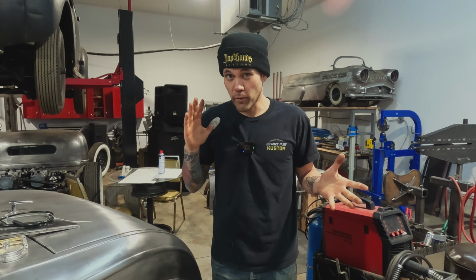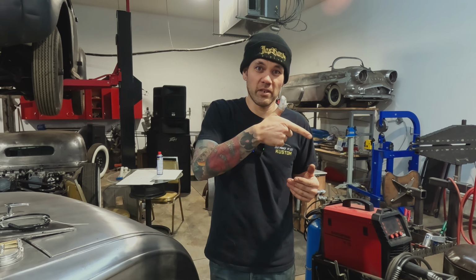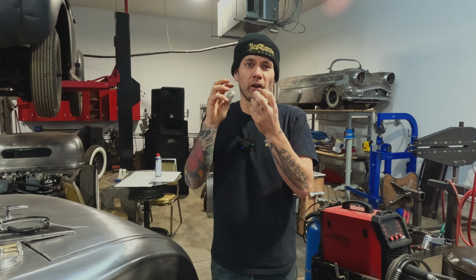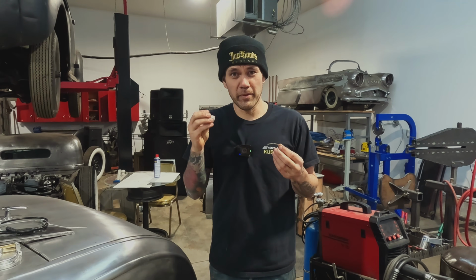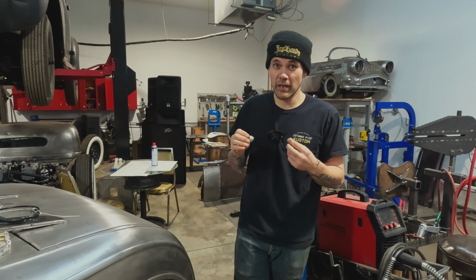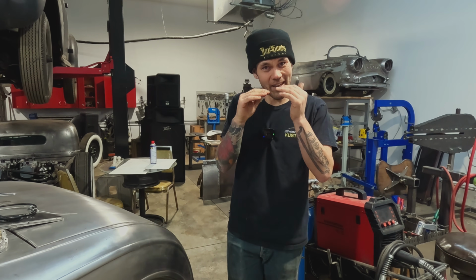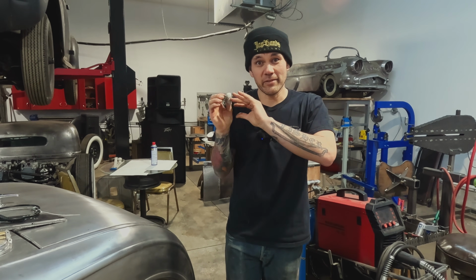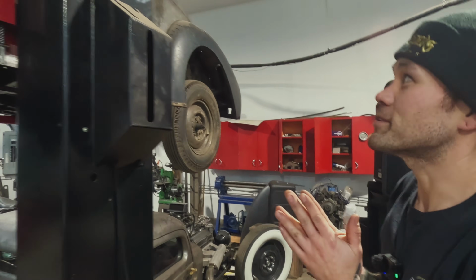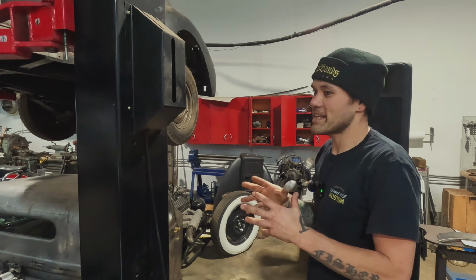So if you're going to be doing that with MIG, it's not really possible. You're gonna just deposit so much material that you're gonna have tons of material to grind off. It's gonna happen so quickly that the hot and cold makes it brittle, along with the extra material deposited, so you're just not going to enjoy hammering out your weld if you're MIG welding. So a TIG weld can be nice, small, precise, tight fit, and is still soft enough that it can be hammered. Whenever we're TIG welding sheet metal, it is your best case scenario. It's closest to gas welding.